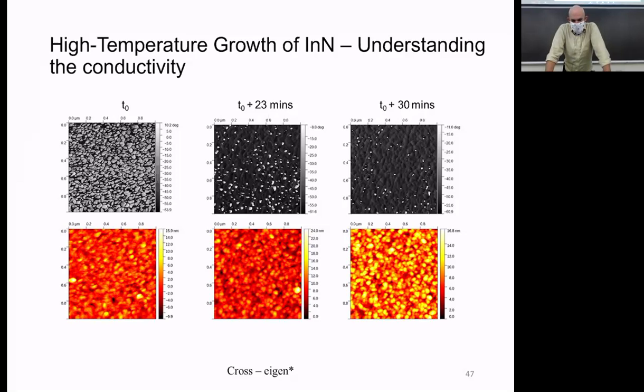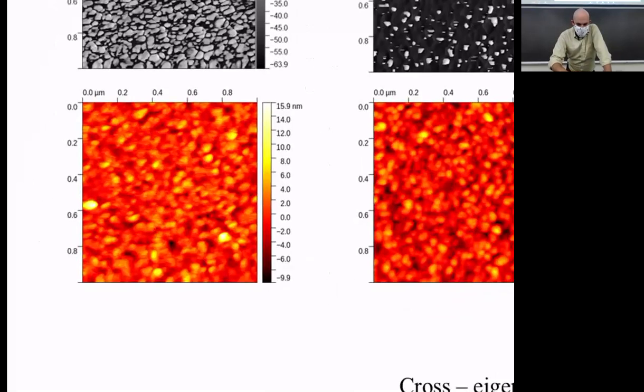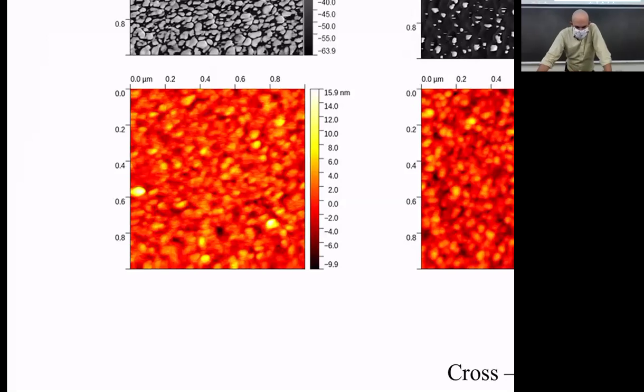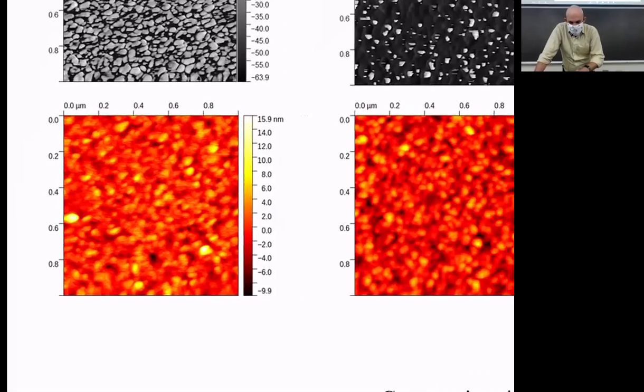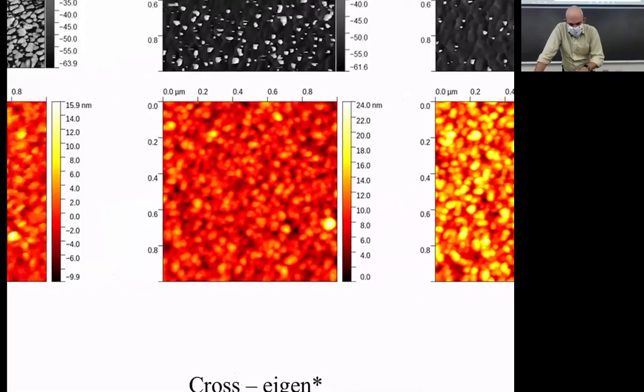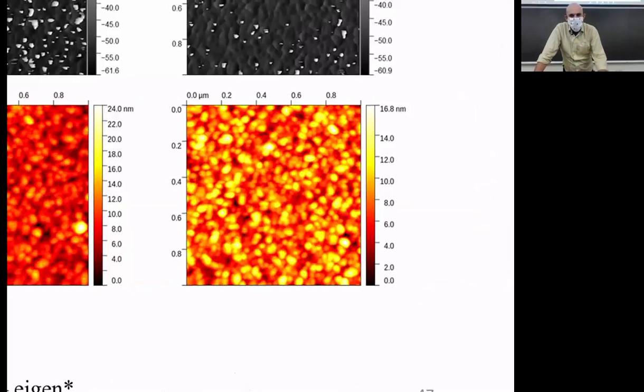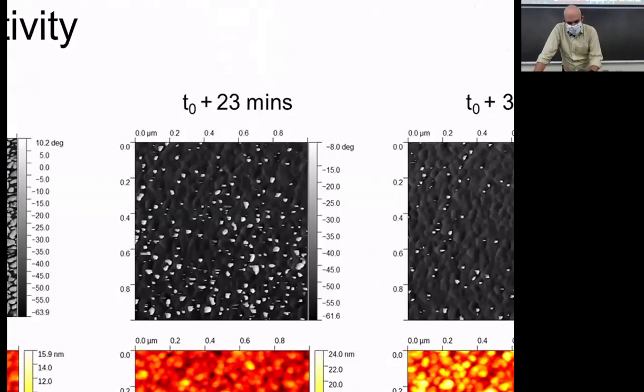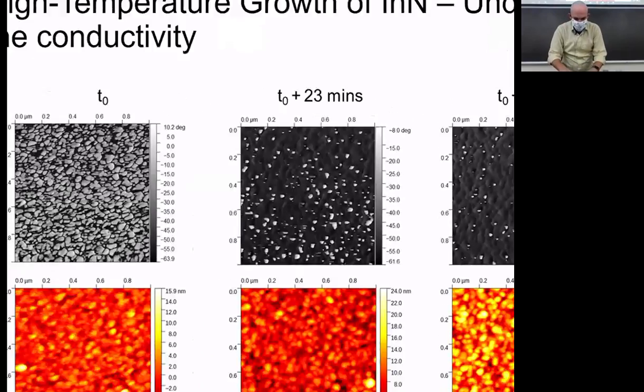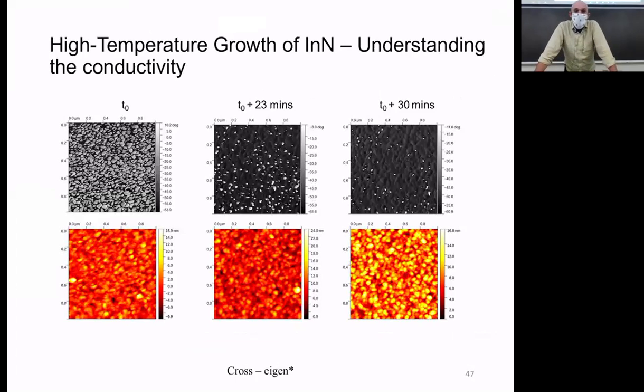And one of the things that was interesting about these samples while I was working on them was that trying to do the AFM measurements of them did something interesting. You can see on the left here, we noticed that we were getting like a double image. And I am actually going to intentionally zoom right now. You can see over here, if you look at this picture, there's like an outline and then a second outline on each of these particles, each of those little clusters. And as time goes on, that double outline changes until the image clears up. Now, what I'd done with the sample was that I'd actually grounded it.